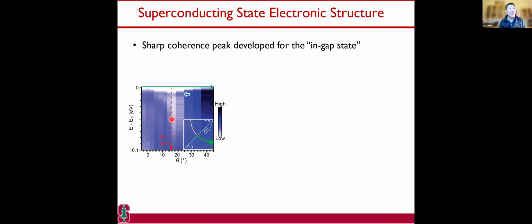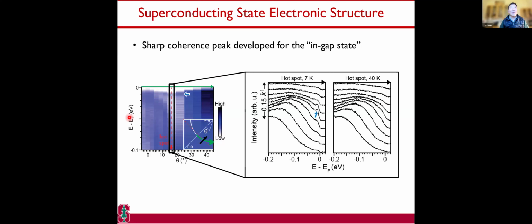I hope you also see that at lower energy, there's another feature following this way. And I'll prove to you this one turns on only below the superconducting transition temperature and is the Bogoliubov quasi-particle. Okay. Now let's take a piece of that. This feature is the high energy feature, the high energy pseudogap. And this feature is this little blue peak. You can see that it's not there above TC, but it's clearly identifiable below TC.